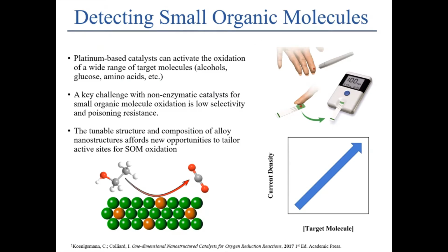So the focus of this work is on looking at how we can use these catalysts to detect small organic molecules. So platinum is a great catalyst, and it can oxidize a wide range of targets: alcohols, glucose, amino acids. But the problem is if you have a good catalyst that can oxidize a wide range of molecules, the question becomes, if you want to have this be a selective catalyst or a selective detector, meaning it only oxidizes one thing, how do you do that? How can you develop a catalyst that normally oxidizes a broad range of molecules, but you've kind of toned that activity down to make it just active toward one particular functional group or one particular type of molecule?